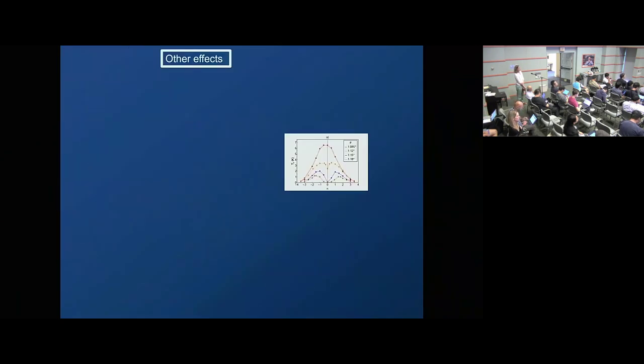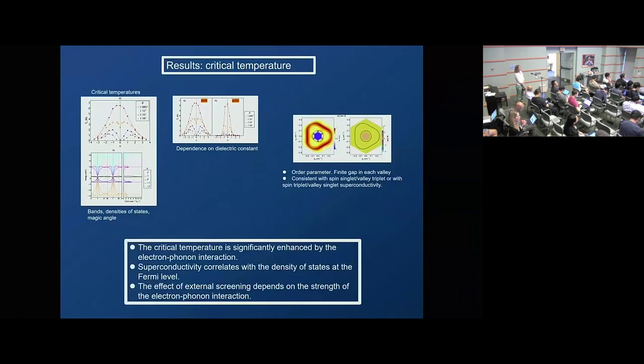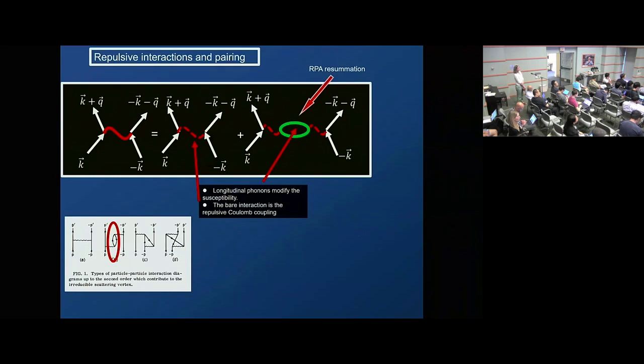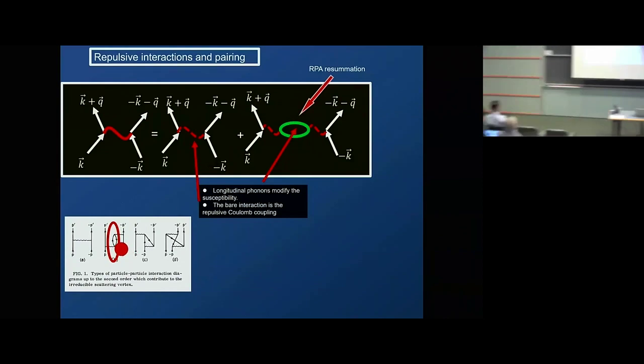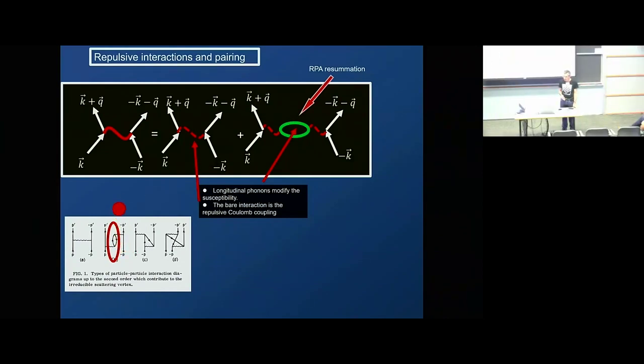Here you see the Kohn-Luttinger scheme. This is not the only diagram we have. We have many bubbles connected to bubbles, and then connected to the other Green's function. Between bubbles, we inserted longitudinal acoustic phonons, because an electron-hole pair can decay into an LA phonon and, in addition, induce another electron-hole pair. So the initial interaction is always repulsive, and phonons only renormalize the propagation of these charge fluctuations. But if you kill the electric charge, you kill the superconductivity. So in order to have superconductivity of this type, you need a repulsive interaction to start from.